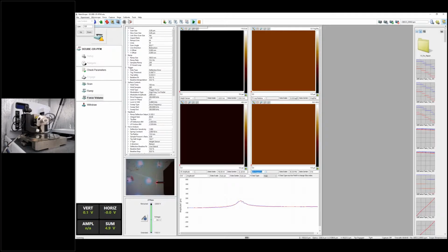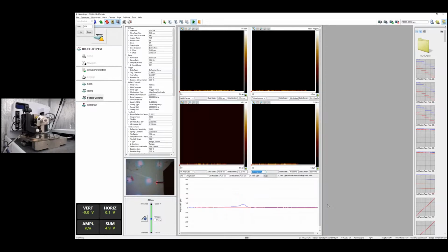So now we are all set. We can start the scanning. So in the bottom window here, what you are seeing is that at each pixel, the AFM is trying to sweep the frequency, and based on this amplitude versus frequency plot, it's trying to fit this plot to find out the real contact resonance at each pixel. So the blue line is the raw data, which is amplitude versus frequency data, and the red line is the fitting line. So you see some oscillation, some noise, especially when I talk.